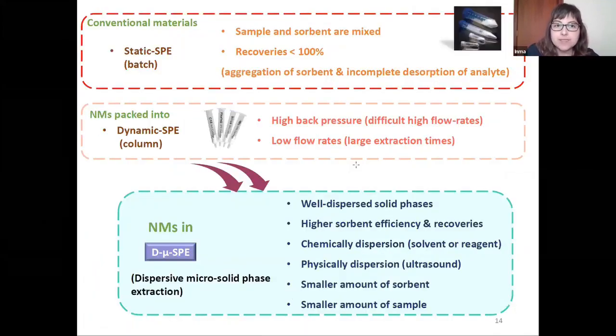In the static or batch solid phase extraction with conventional materials, the sample and sorbents are mixed. However, recoveries can be lower than 100% due to the aggregation of the sorbent and also due to the incomplete desorption of analyte from the sorbent. When nanomaterials are packed into dynamic solid phase extraction, there are some problems, such as the high back pressures that can be produced, thus making high flow rates difficult. As a consequence, if we use low flow rates, larger extraction times are produced, which is also undesirable.